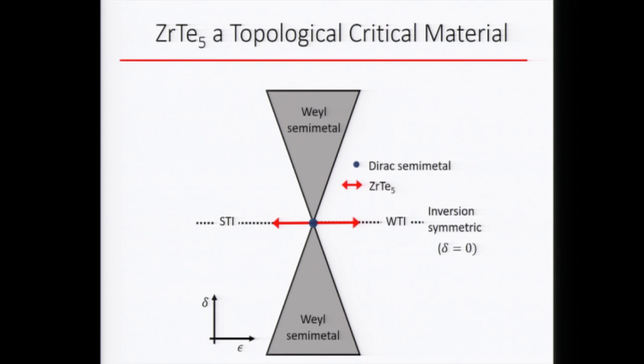Yeah, go ahead. So is it understood at zero strain what the electronic state is? Is it like a strong TI, or like a weak TI? I think there are more papers favoring weak TI. Again, I think one of the difficulties is that you have a very small gap bulk electronic structure, which looks like a Dirac dispersion, and you're looking for another two-dimensional Dirac dispersion on top of this Dirac dispersion. And this bulk Dirac dispersion is also quite two-dimensional because it's a layer structure.